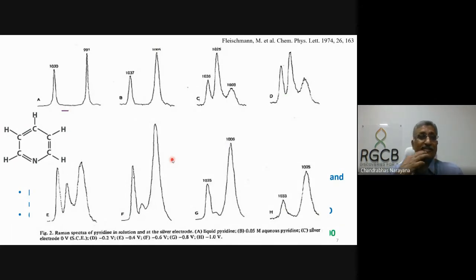Now, to show you that there is indeed chemical enhancement and also an enhancement due to electromagnetic radiation, the first discovery was done by a very well-known scientist in electrochemistry. His name is Fleischmann. He was looking at an electrochemical cell, and he was doing Raman on the silver electrode, with pyridine. And he realized that if you take normal liquid pyridine, this is how the spectra looks. And if you take a very low concentration of pyridine, about 0.05 molar, your signal reduces, but you can actually see the signal. But the moment you look at pyridine around the electrode, he sees that the spectra is quite different from that.